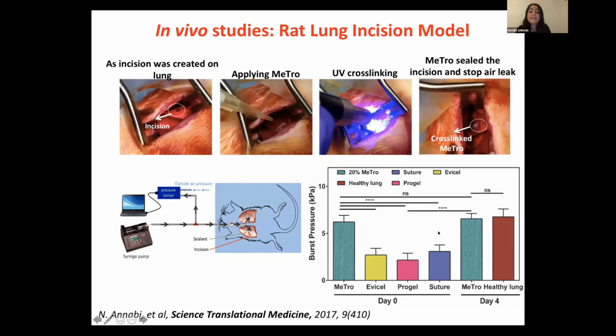And then following this experiment, we did a burst pressure test. I put the scheme here for the burst pressure test. We connect the lung to a syringe pump so we can apply air. And then there is a pressure sensor here. As the lung bursts, we can measure the pressure. And this is reported as burst pressure. Here you see data for ex vivo. This is on a dead animal.